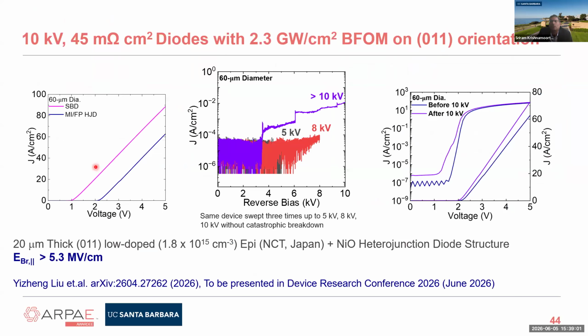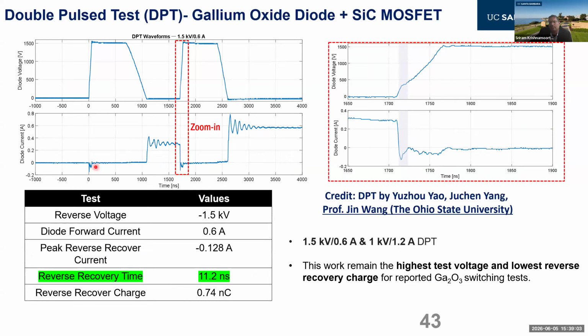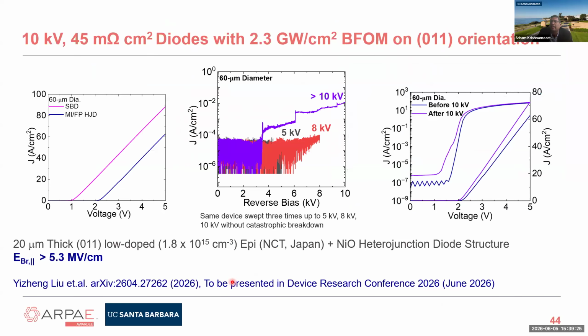So now these diodes have some of the highest test voltage and lowest reverse recovery charge reported for gallium oxide, and these numbers are promising. We did some benchmarking with silicon carbide, and the reverse recovery time is definitely smaller than silicon carbide at similar voltage rating. So that's quite exciting, and we continue to push some of these very recent results.